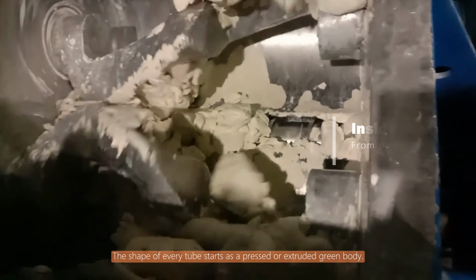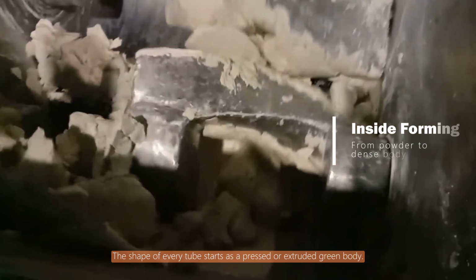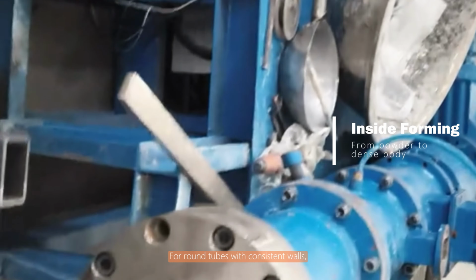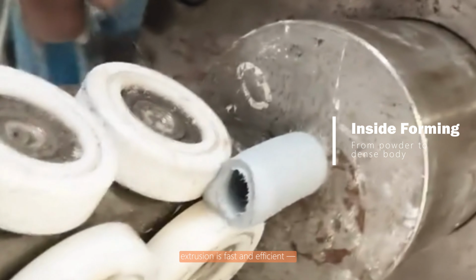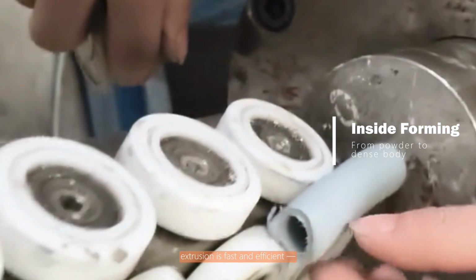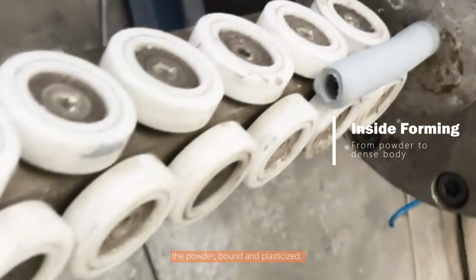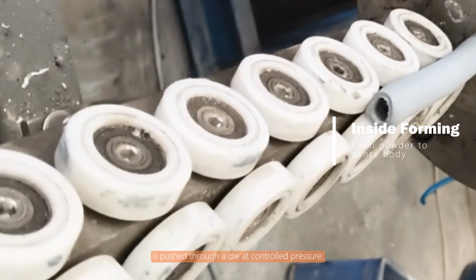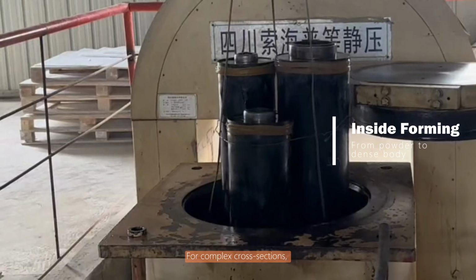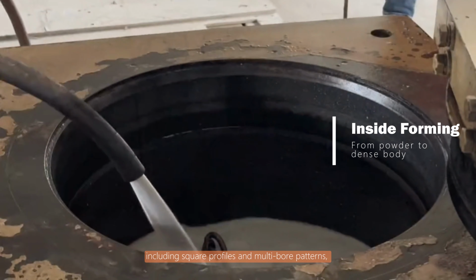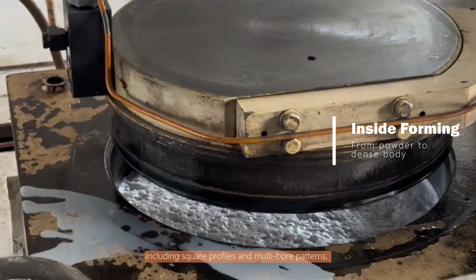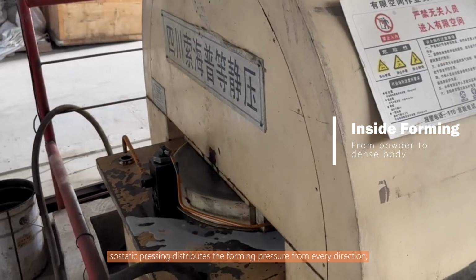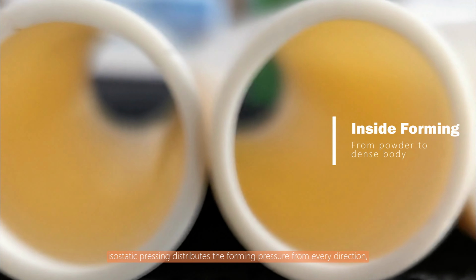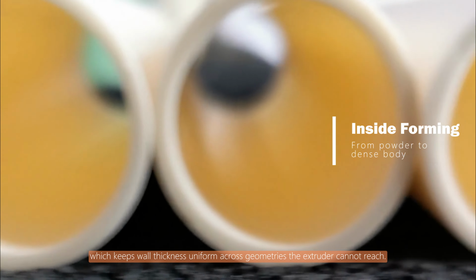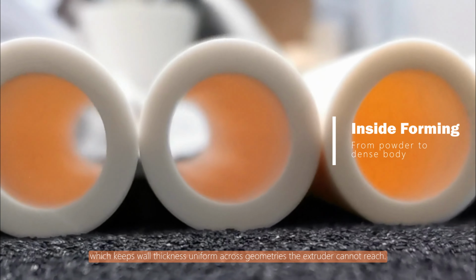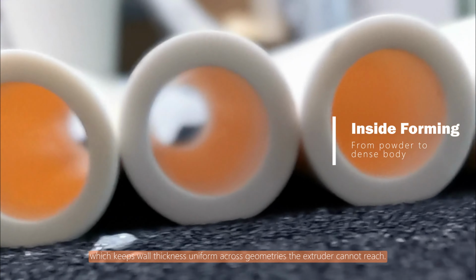The shape of every tube starts as a pressed or extruded green body. For round tubes with consistent walls, extrusion is fast and efficient. The powder, bound and plasticized, is pushed through a die at controlled pressure. For complex cross-sections, including square profiles and multi-bore patterns, isostatic pressing distributes the forming pressure from every direction, which keeps wall thickness uniform across geometries the extruder cannot reach.